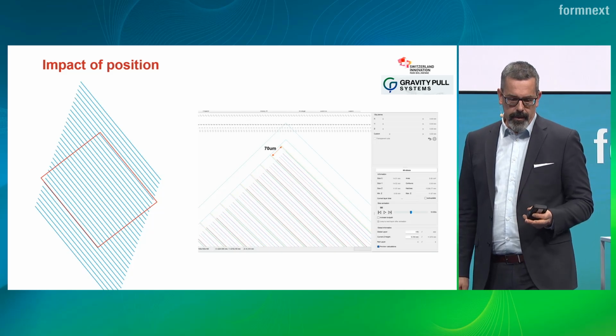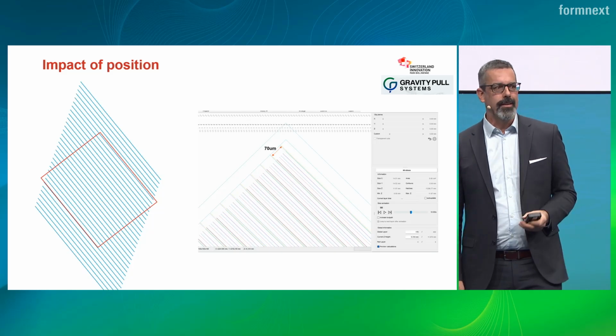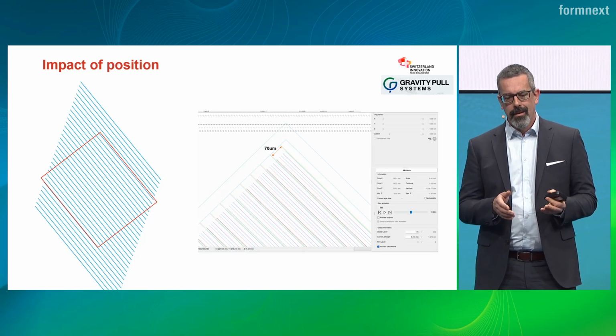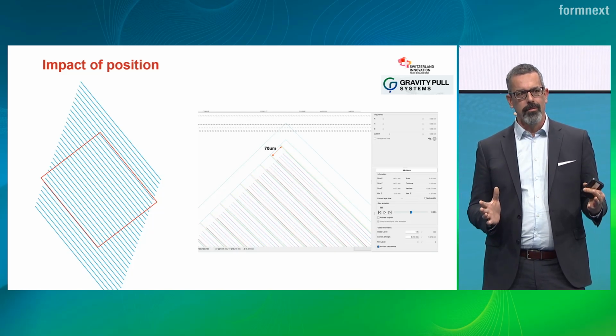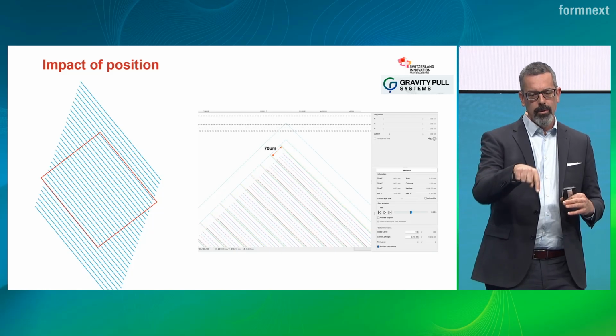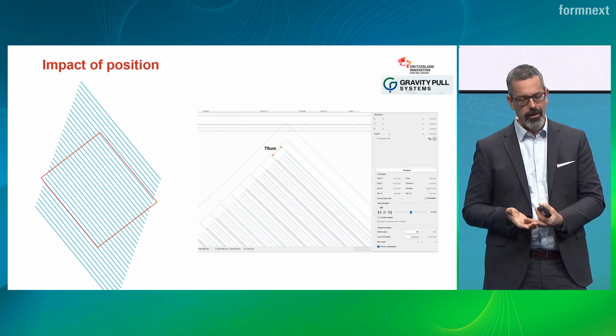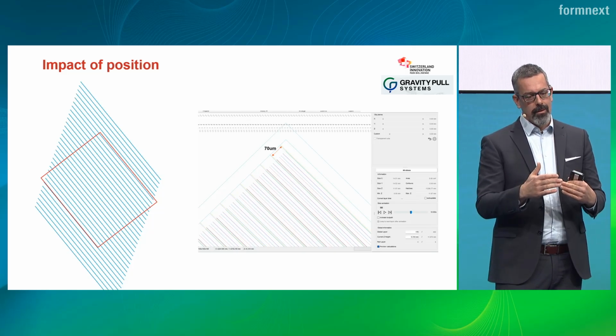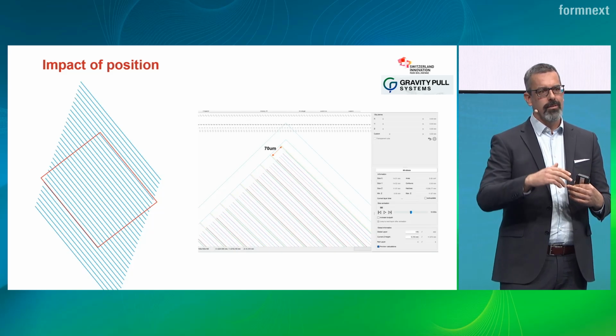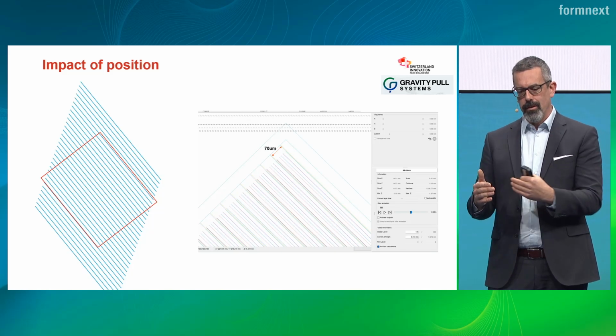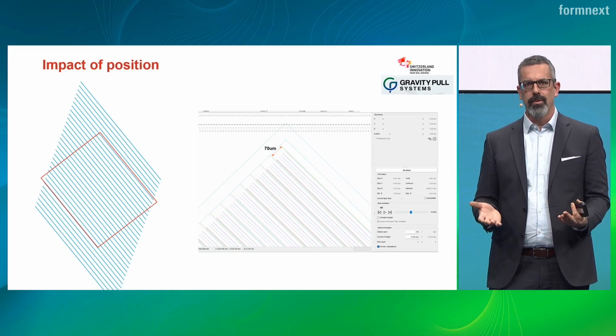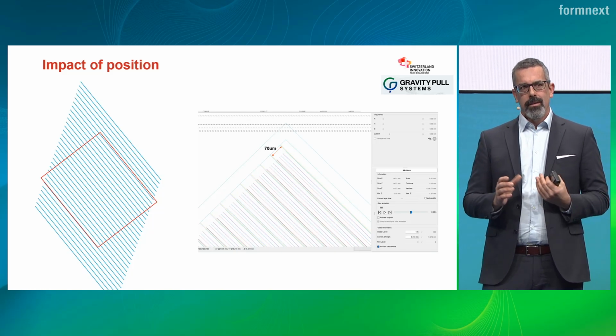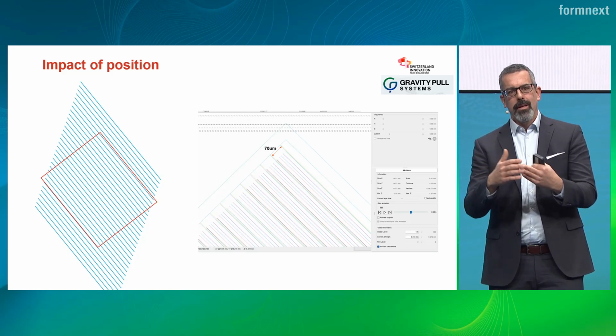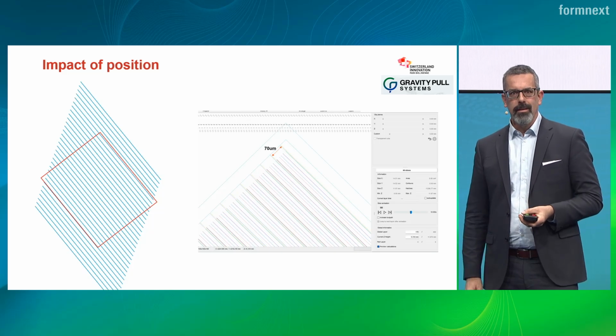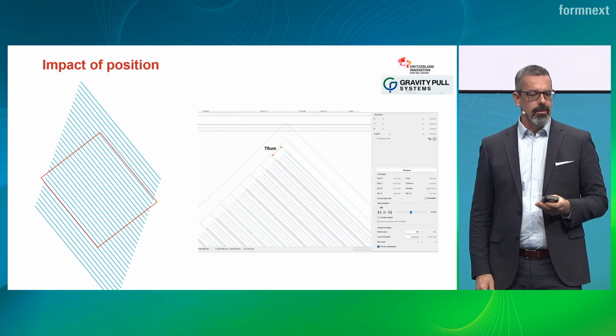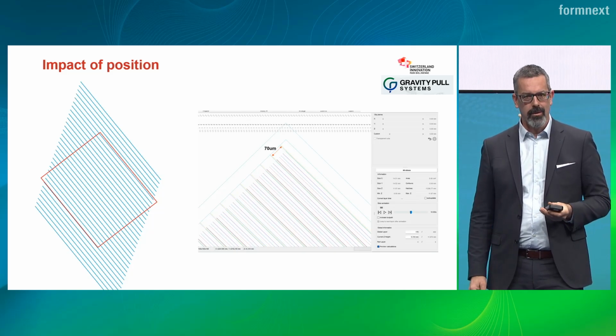Yes, I will skip. There's an effect that you're maybe not aware of. If you create a hatching, the slicer usually creates a hatch on the platform level. And then you add your part and you kind of cut out from the existing hatch the cross-section of your part. So now, depending on where you place your part, it might include or not one vector more or less. And indeed, the variation of the positioning of the vectors that you can get is up to 70 microns. So that's just by placing the part. So this can explain sometimes why placing a part in a different location of the build platform can lead to a different result, or that it can fail in another place if you add more of the exact same component.